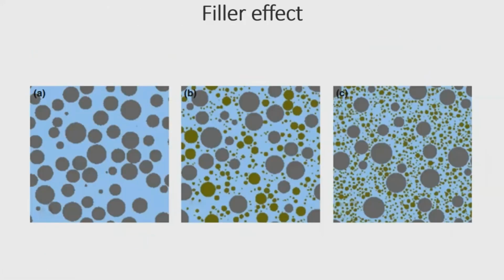Not all biochars tend to react with cement in a pozzolanic way or in a latent hydraulic way, and might be a strong candidate for the filler effect, which is the filling of voids, and these particles act as nucleation sites.